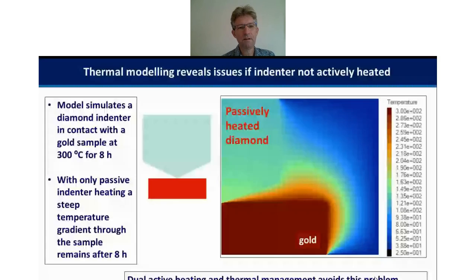So firstly, if we consider what might happen if we simply have a hot sample and we indent that hot sample, then we might get heat flow. One of the things that people have looked at is they said, well, maybe it's okay just to put the indenter in contact with the sample, leave it for a certain amount of time, and then it will reach a thermal equilibrium, then we can do the test. Some manufacturers have gone down this route, and over the years it's become progressively less popular as it's been realized that really it's ineffective, typically in a large majority of situations, particularly for conductive samples. And this thermal model is indicating why, that you don't really approach a thermal equilibrium.